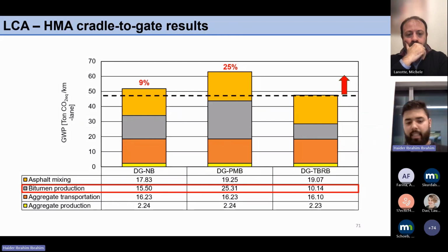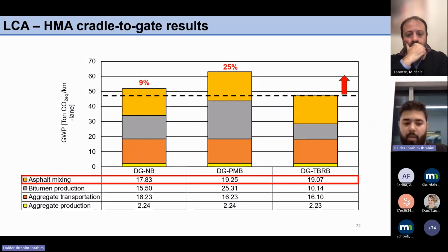The asphalt mixing is lower for the DG neat bitumen because of the lower mixing temperature, which was around 155, compared to DGPMB and DGTBRB, the modified ones, which were mixed at around 170 here.